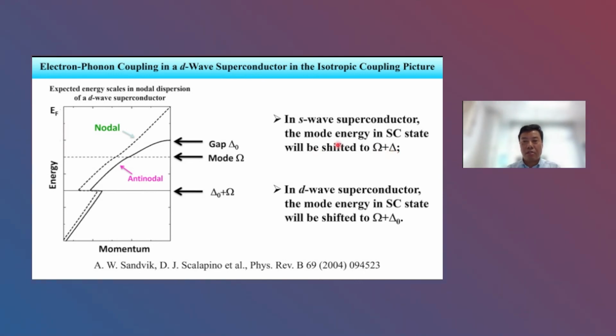So for the S-wave superconductor, the mode energy should change from the initial phonon energy omega to omega plus delta, the superconducting gap. And even in the d-wave superconductor, similar analysis also indicated that the kink energy should move from the initial omega to omega plus delta nought. But why don't we see this?